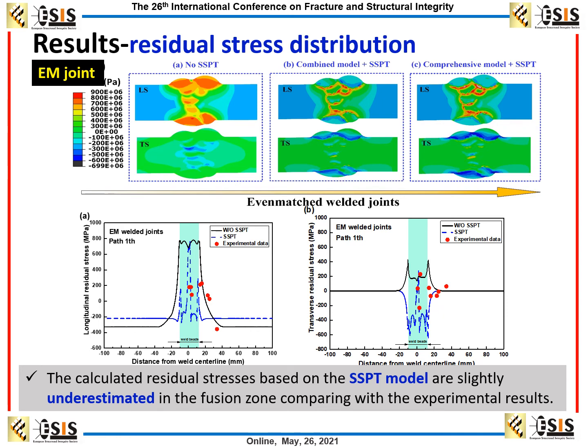This is the result of residual stress distribution of the even matched welded joint, and from this result we can see that the residual stress distribution considering the SSPT effect gives good agreement with the experimental data in the longitudinal residual stress. For the transverse residual stress, we can also see the same conclusion from the figure. So the calculated residual stress based on the SSPT model is slightly underestimated in the fusion zone compared with the experimental result.